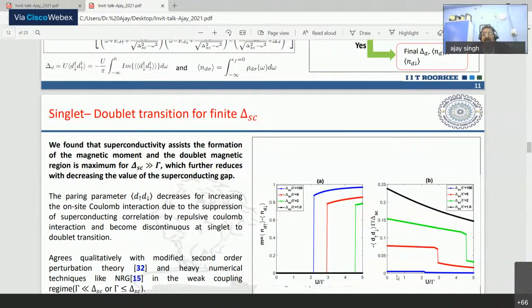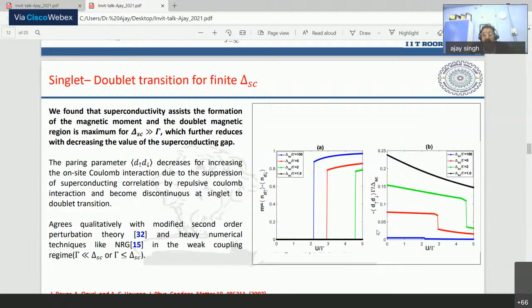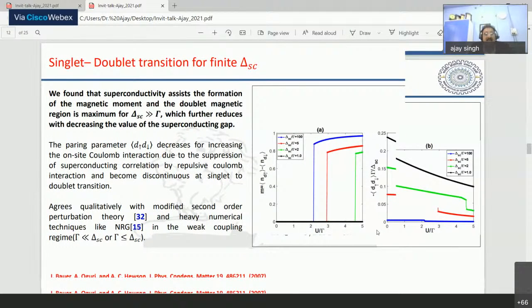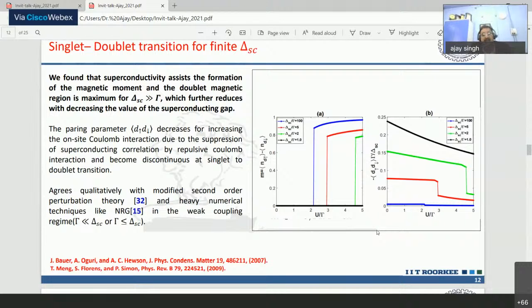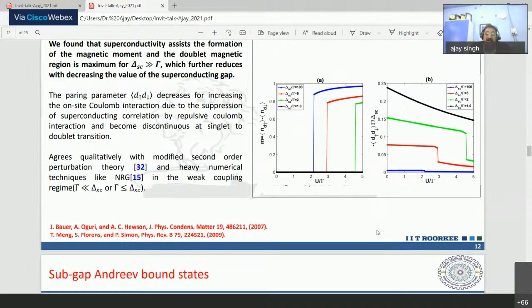And we found that this magnetic moment and the resonance superconducting pairing on the dot have opposite effects. The time the magnetic moment is suppressed, the resonance of the paired state on the dot starts becoming robust. So these are very interesting results beyond the single impurity Anderson model, which basically show a singlet doublet transition as well as a very reverse effect, which is supported by experiments, that the superconducting correlations may make a magnetic moment grow on the dot if it is close to the Fermi level.